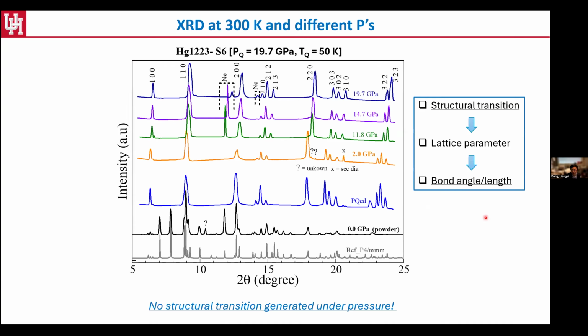So we start to look into it more microstructurally. Some hypotheses we have are whether there is some structural transition that people haven't really paid attention to, or some structural transition that only happens during pressure quenching. That's possible. And when we did a few runs of synchrotron X-ray, also in collaboration with Team's group, we came to the conclusion that indeed there's no structural transition, either under high pressure or during pressure quench.